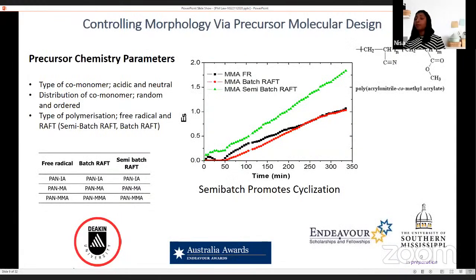We made a comparative study by selecting 3 co-monomers, and we carried out the synthesis using both conventional and controlled polymerization techniques. We included both acidic and neutral co-monomers in our study, such as itaconic acid, methyl acrylate, and methyl methacrylate. And we used free radical as well as RAFT polymerization methods for the design and synthesis of all these polymers.